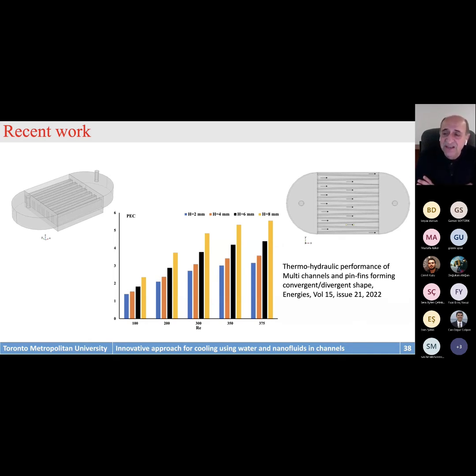And what we notice is that the convergent channel is a good way to use, because the flow starts very slow, and this is the place where the fluid boundary layer is very thin. As the flow progresses, the boundary layer increases, but because it is a convergent channel, the velocity increases, meaning destroying part of the boundary layer as it leaves from the other end.